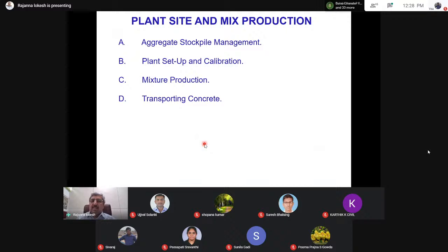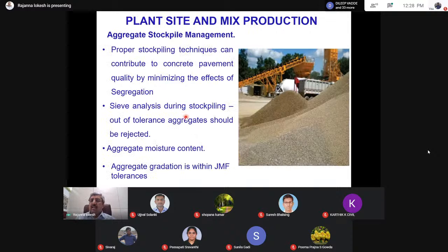So the next parameter will be site and mix proportion: aggregate stockpile management, plant site setup calibration, then mix proportion and transportation of concrete. When we are using different sizes of aggregates, say 12 mm, 20 mm, and sand, it is all the more important to stack the aggregates in different stock piles so that the required percentage of materials could be used for production of 1 cubic meter of concrete. So proper stock piling technique can contribute to good concrete pavement.